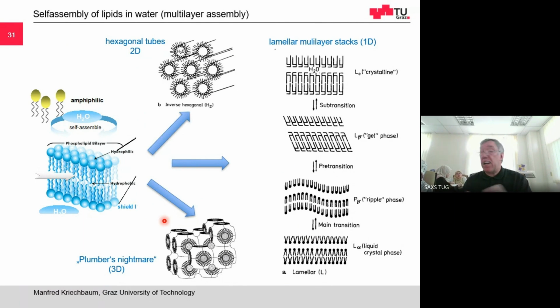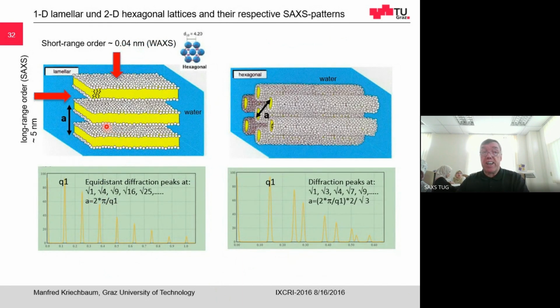You may also be able to make not only single shell liposomes or vesicles, you can also make multilamellar. So the infinite number of multilayers of these bilayers, always separated via a water layer. You can make this one-dimensional lamellar, two-dimensional hexagonal. In that case, the water is in these cylindrical cores, or you can also make three-dimensional complex structures. Here again, this multilayer lamella. So you have bilayer, water. So there's an infinite stack. And with SAXS, you get the information about the long-range order.